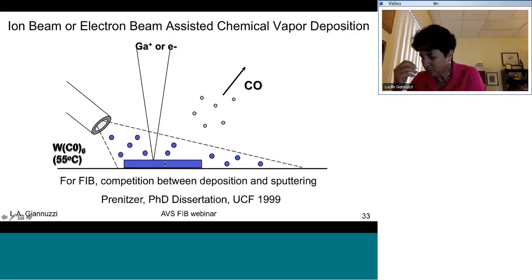And I want to make a point here that this deposition is line of sight. So if you have a sample with a lot of topography and the gas can't get to the region that you want to deposit on, then you're not going to form a good deposit. So the gas has to be able to get there. It has to be line of sight. So if you're working on something that has a lot of topography, in some cases you want to either turn your sample at a particular orientation relative to the gas injector system, or you want to make your pattern in line with where the gas is coming from.